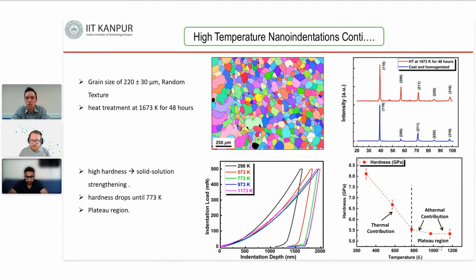A question here from Suyash, who asks, what is the required surface condition for nanoindentation? I guess roughness, any preparation before nanoindentation that is recommended? Generally speaking, in terms of nanoindentation, the lower the surface roughness, the better. I think the ISO standard states that the surface roughness should be 20 times lower than the maximum indentation depth. So the maximum indentation depth is 20 times the Ra value.